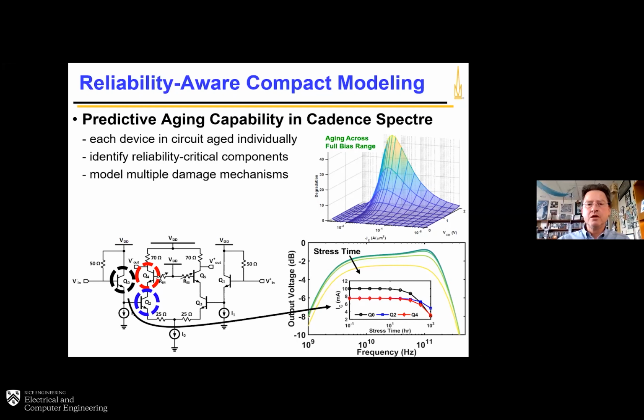And you've also very likely, if you stayed in that boundary, thrown away performance of the circuit itself. Wouldn't it be cool instead if I had a model which, when I was done with my nominal design, I could swap in and run what it's going to look like 10 years later from a reliability perspective? And then I get a very quick idea of what matters and what doesn't. And I'm able to come back now iteratively and do a more robust, higher performance design, which still in principle is reliable in system usage. And that's been a holy grail, if you would, for a long, long time, and one that my team has been working toward for a few years, and are still working toward. But you can see the amplifier on the left. You can now come in and swap in these reliability models and begin to look at what aging happens in the circuit. We're not there yet, but we're getting close to that.